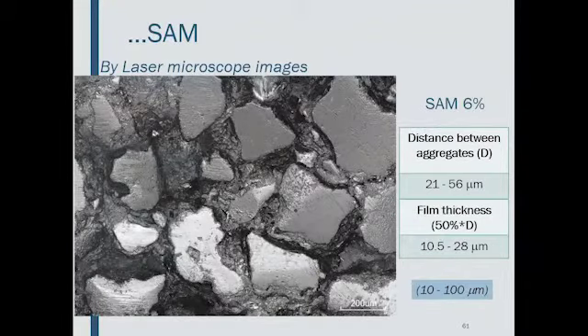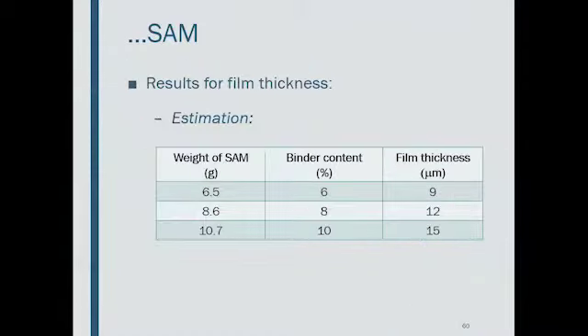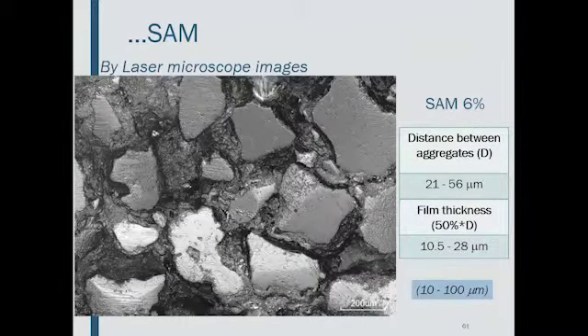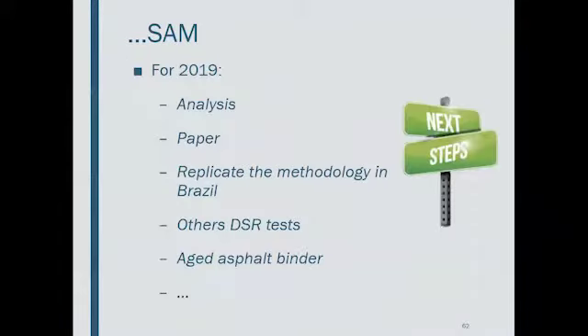And with the laser microscope images, you can see the aggregates and the space between the aggregates with the binder. Then we can get this distance and consider that the film thickness for each aggregate is half of this distance. Then you can get numbers of about 10 and 28 micrometers, and they are close to the estimation. And also, we believe that they are in the range that you want to work in this study.